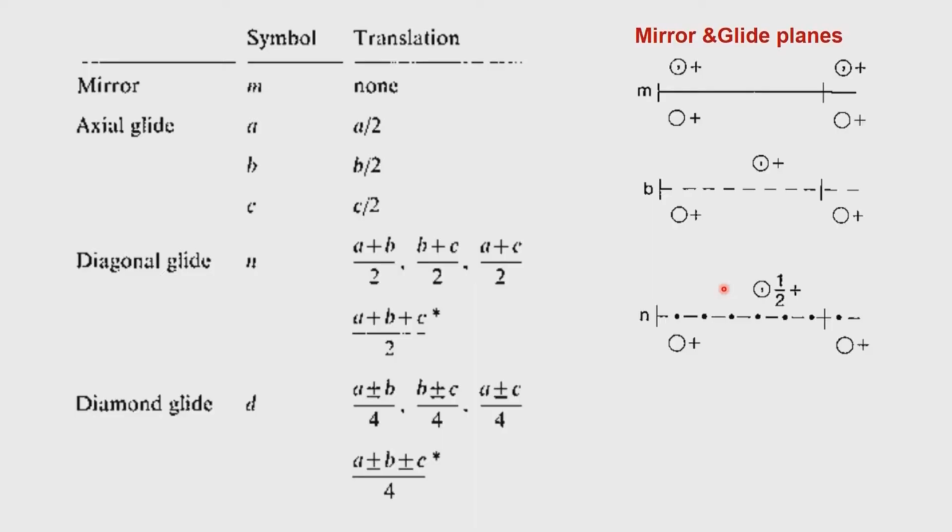So, effectively we are going along the diagonal. So, you have this translation half unit, and then we go half above, which is now parallel to this plane. So, the plane is like this. So, we have two translations, one down here and another going up there. So, effectively you have this half plus also coming in here. This half plus tells us that it is an n glide, and the notation for the n glide is a line and a dot, that we know already from our early classes.